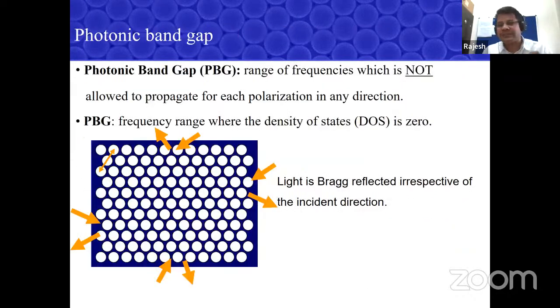Now, the take-home message, what you should understand: a photonic band gap originates because of the periodicity in refractive index. And this periodicity in refractive index happens at the optical wavelength scale. You can have it in the near infrared, you can have it in the microwave, and it depends on where you would like to have your band gap, depending upon your interest and applications. And these are mostly man-made structures. Unlike a semiconductor, where you don't need to place the atoms by yourself, here you have to really make the structure. So experimentally, it became a real challenge to make these structures and measure these things. Even photonic band gaps still remain a challenge for people to measure.